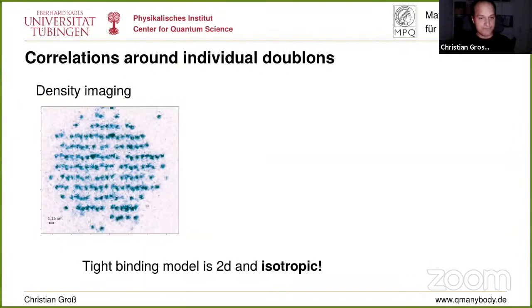And how do we do this? We now need to get our technique. Here comes the imaging technique that I promised, version 2.0. So how do we get this technique to 2D? Well, we don't do much. We just allow tunneling in the vertical direction, even though the distance here is still twice. So we still have the space to do the same superlattice trick as before.